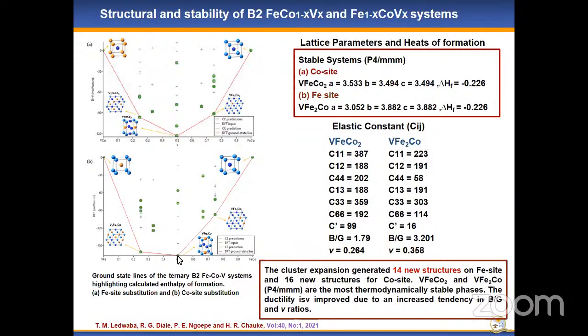Depending on what kind of composition you are interested in, in this case we have predicted about 14 new structures for this system. And this work was also published. It was the work done by Ms. Ledwaba. Very interesting in the sense that you can do different doping sites. You can do the cobalt site, you can do the iron site, do all these predictions and come up with different compositions, check whether they are reliable, check whether they will be useful. This study here is mainly for shape memory magnets, which can be used in many industries, especially the aerospace industry.